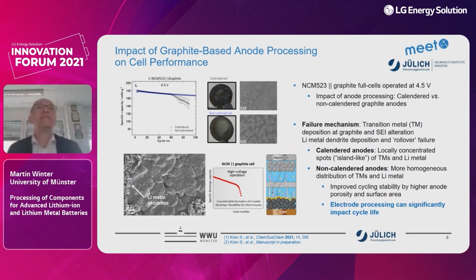Here we see a calendared and a non-calendared electrode. The calendared electrode shows a rollover failure, a sudden death phenomenon. After about 60 cycles, it starts. The non-calendared electrode cycles very well. Basically, in the calendared electrodes we have locally concentrated, island-like spots of transition metals and lithium metal, whereas for the non-calendared we have a more homogeneous distribution of the transition metals and lithium metal.